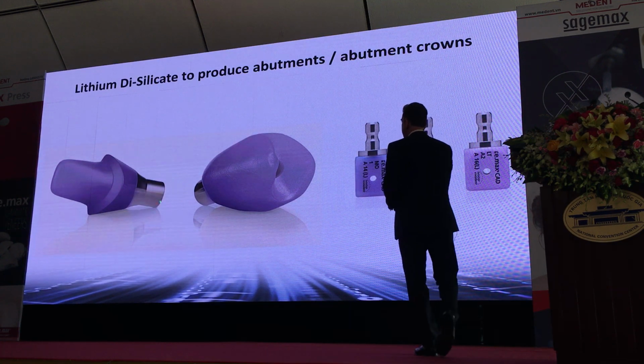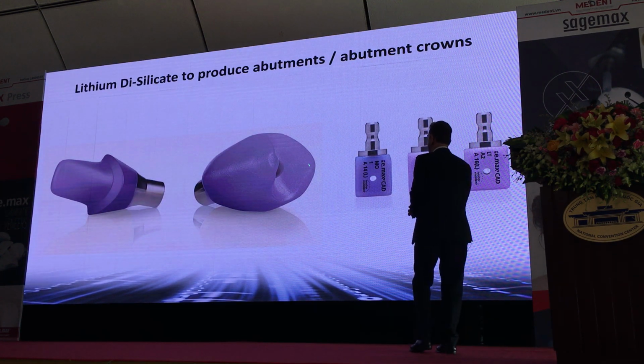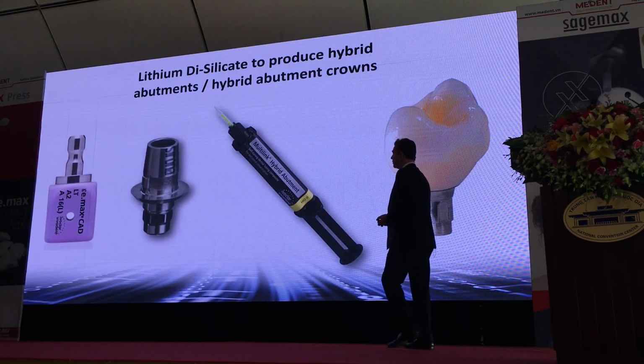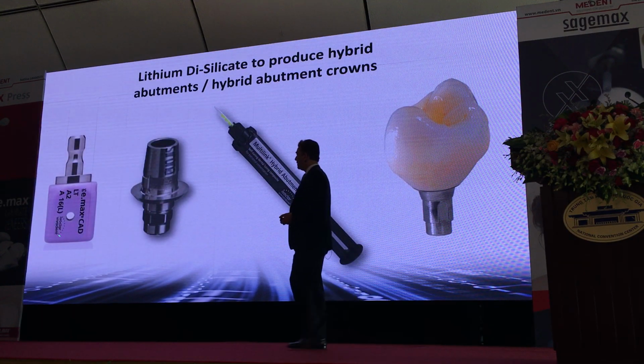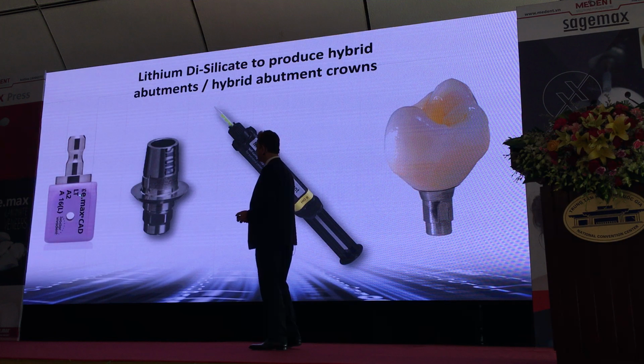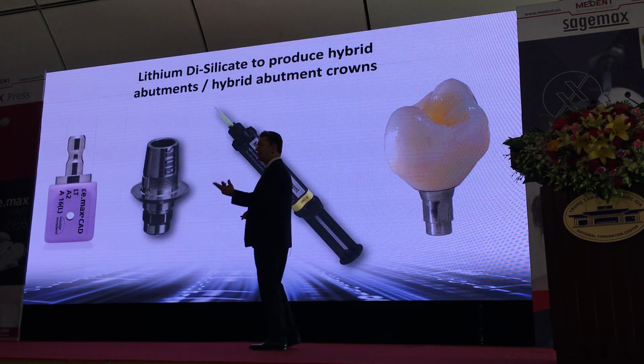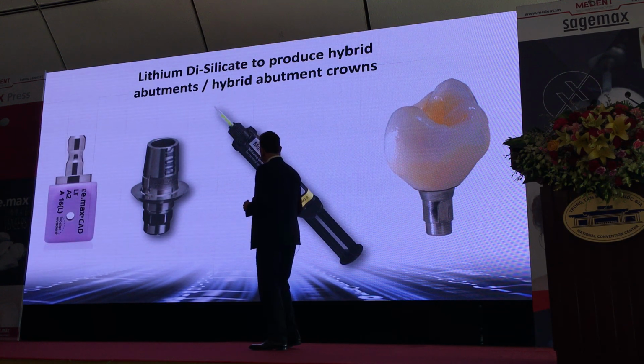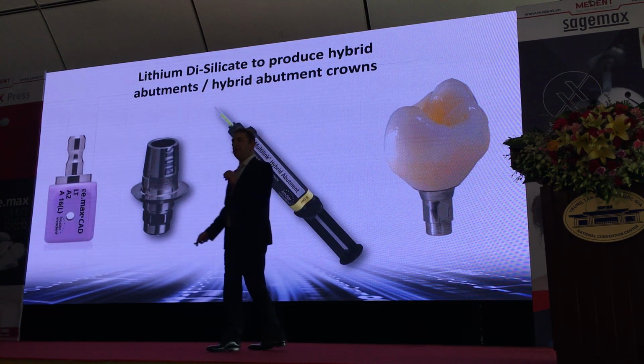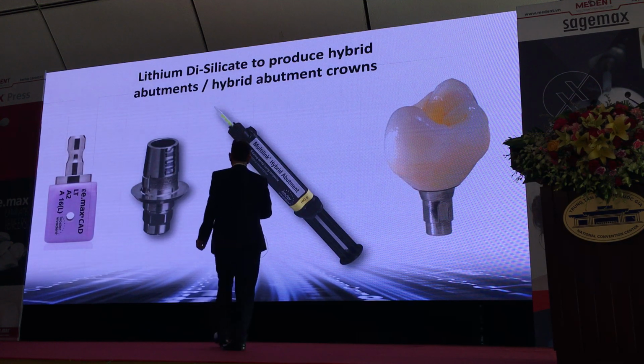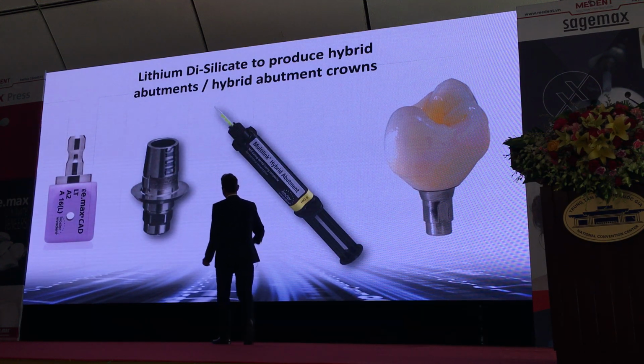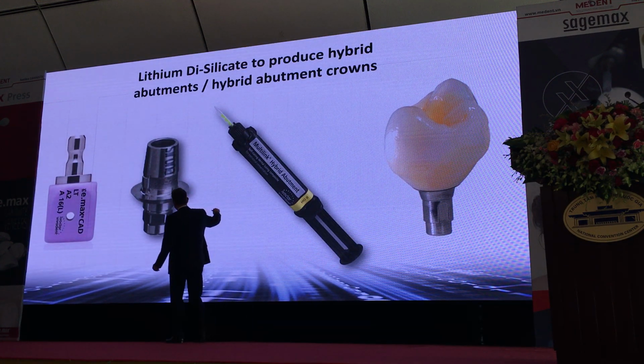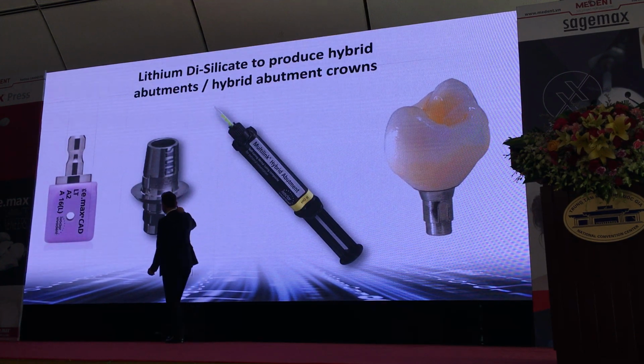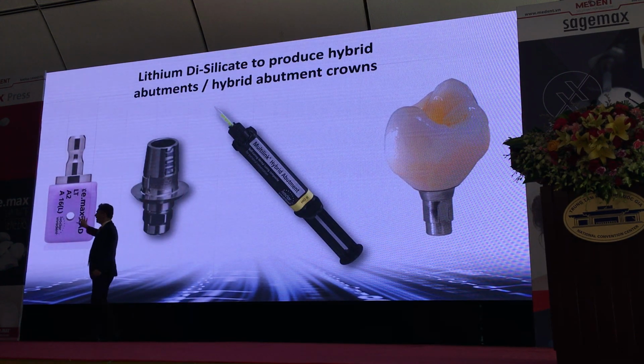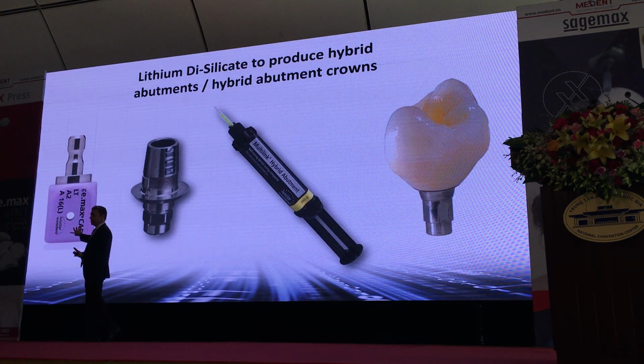So this one is an abutment, and this one is the whole abutment crown. So it works like this. This will be produced first, it will be milled, and then it will be crystallized in the furnace, and then this will be connected with a special cement, which is very opaque. So this multi-link hybrid abutment cement completely blocks out the titanium, so that the titanium is not shining through the restoration. Very important for aesthetics.